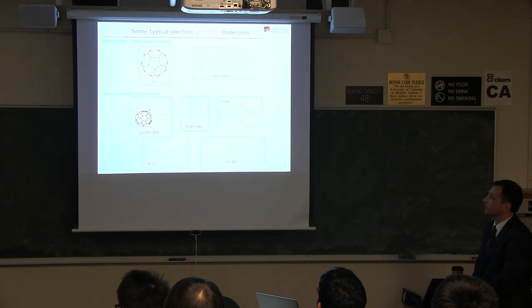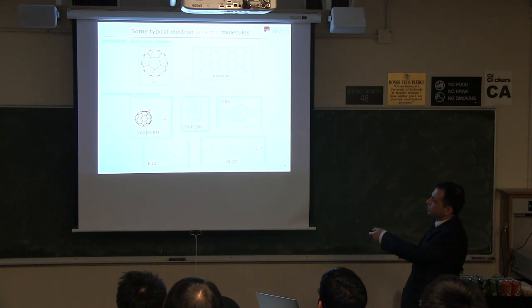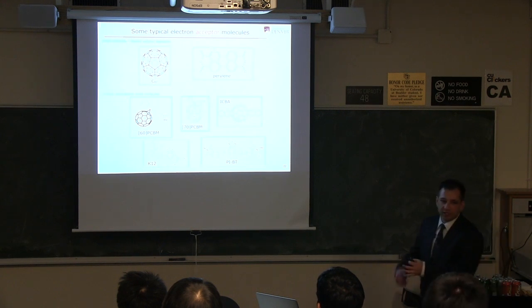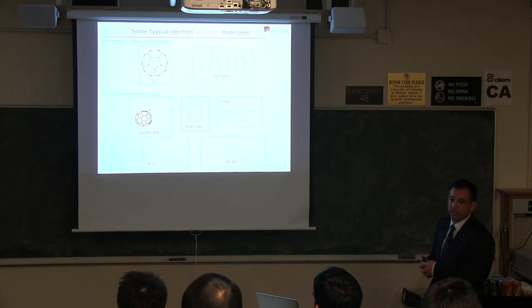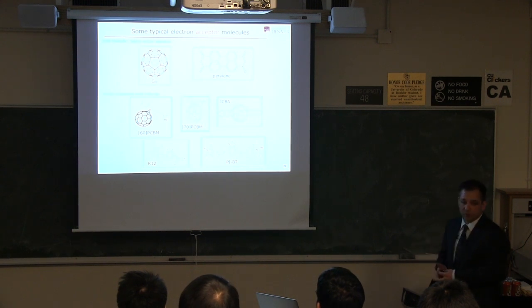Typically we use carbon-60, the buckyball. That is one of the best electron acceptors we have. Perylene also works reasonably well, but not quite as well. Most of these are derivatives of C60, the most common one being PCBM, which is C60 with some side chain on here, or for instance ICBA, C60 with these two groups on the end. Those groups change the electronic structure a little bit, the reduction potential of the fullerene, and that changes the voltage you might get out of the device. More recently, we do have some other materials that act as electron acceptors. They start to look quite promising. Efficiencies are 2, 3, 4%, but still a long way to go.